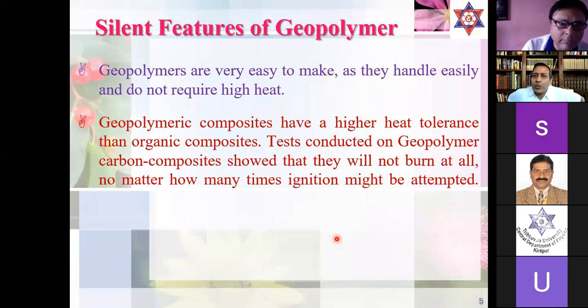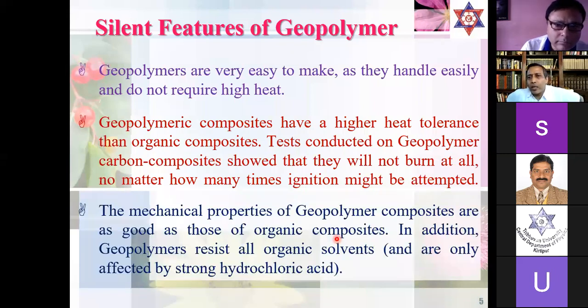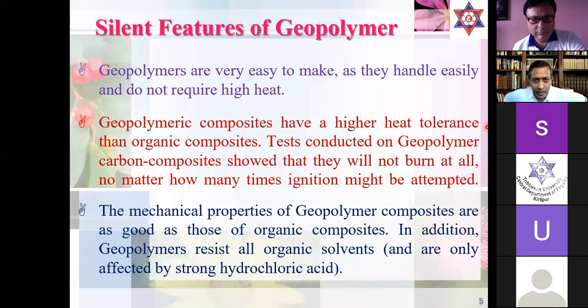Geopolymers are very easy to make, as they handle easily and do not require very high heat. This is the most important part. We can produce cement at about 1600 degrees Celsius and some higher temperatures. But geopolymer, which acts similar to cement materials, can be produced at an ambient temperature of 40 degrees Celsius.